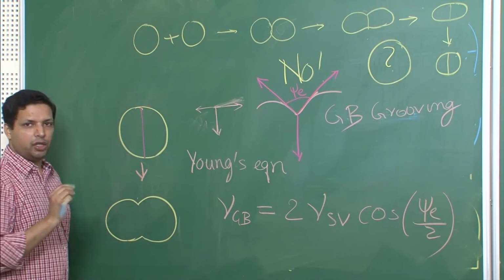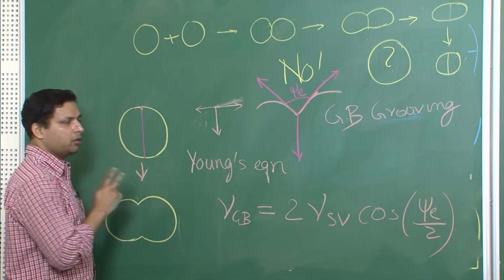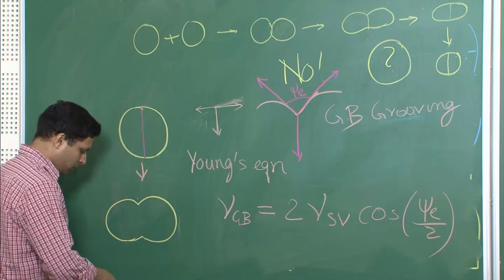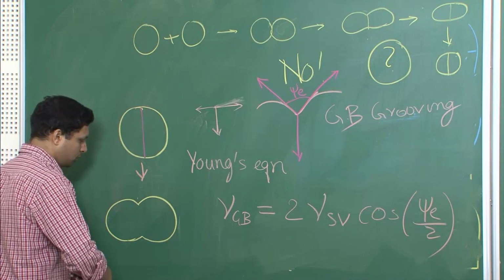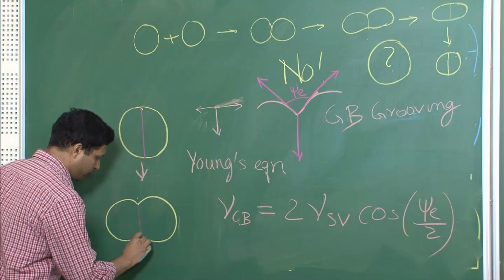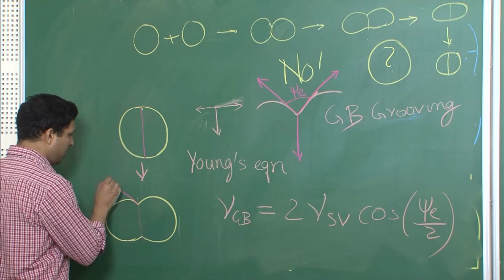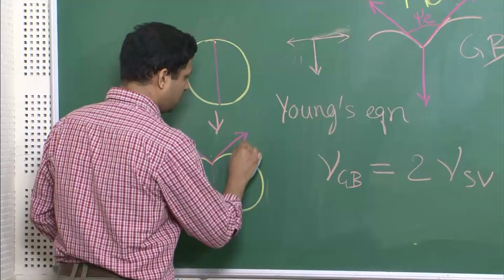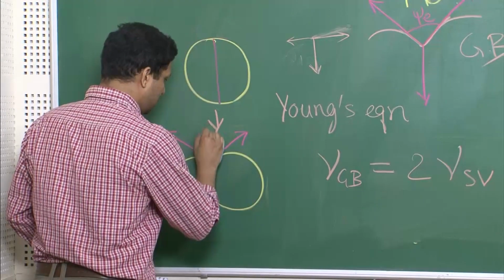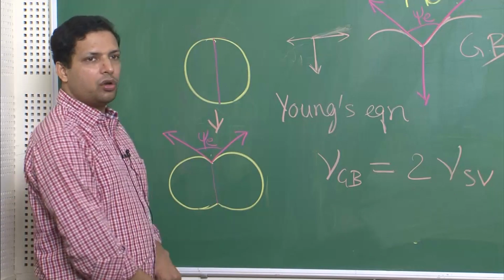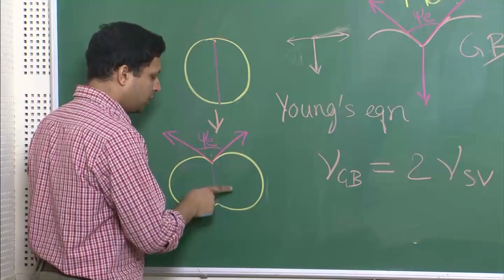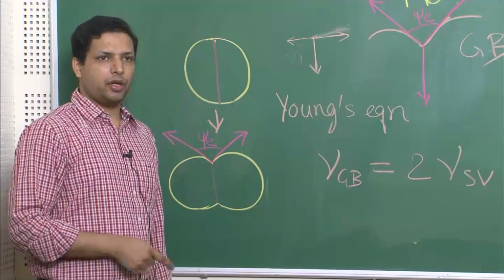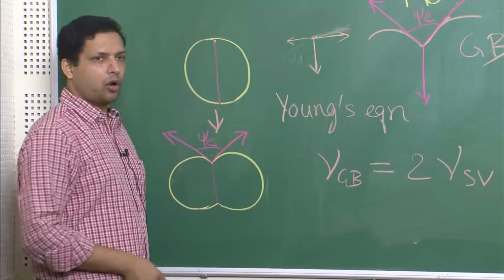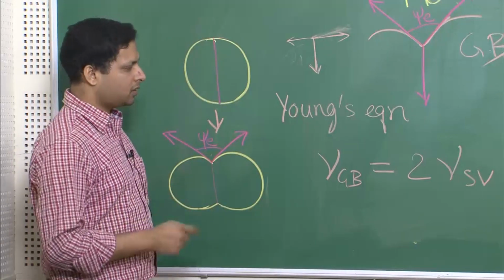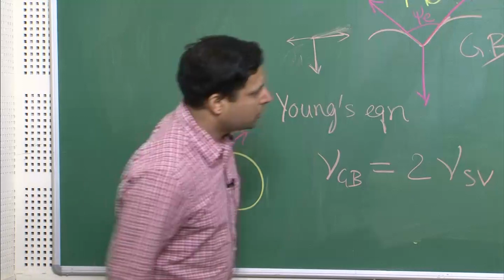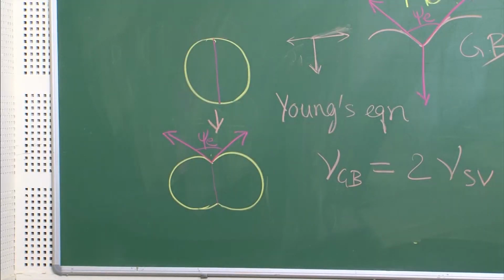Even if you are sintering only two particles, remember, we are talking about only two particles here, and there will be an equilibrium psi E. So, no matter how long you sinter, this shape will be the final shape. It will not change beyond this if there were only two particles, and that means that if we have to look at